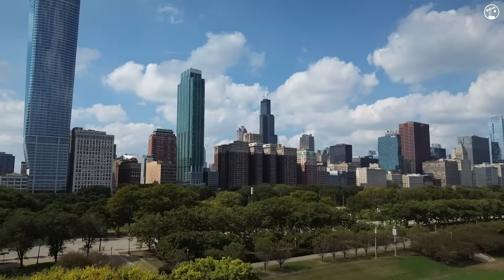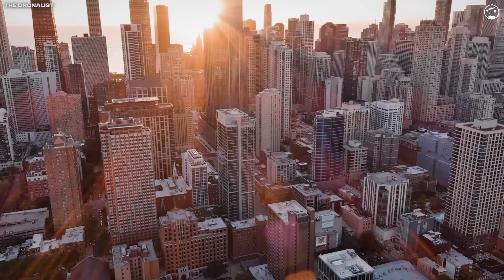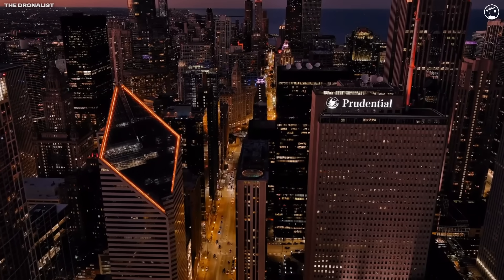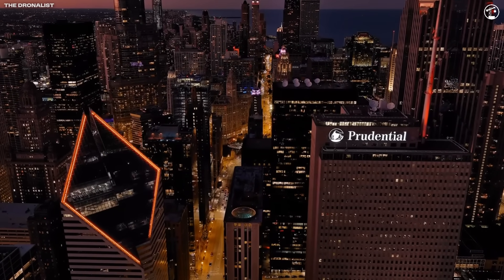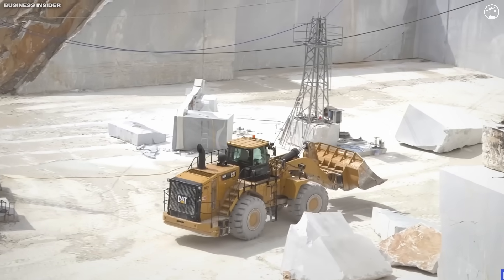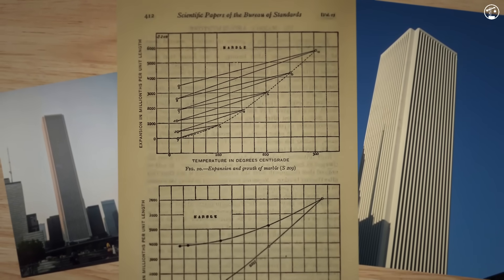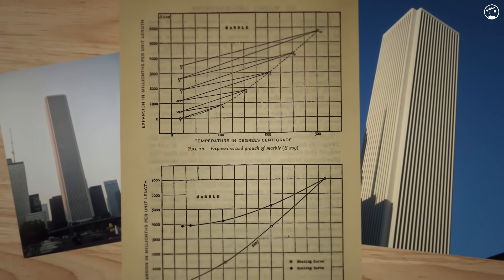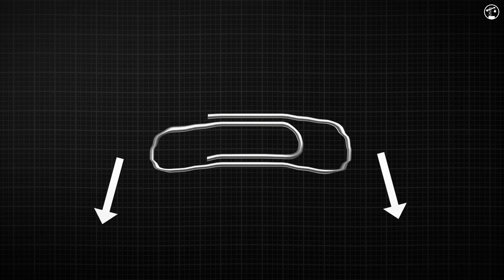Chicago is famous for its windy city reputation, but it also undergoes some serious temperature swings throughout the year. In summer, the facade bakes in 90-plus degree sun, and in winter the temperature can drop into the double digit negatives with bitter winds. That turns out to be terrible for thin marble. Every material expands when heated and contracts when cold, but marble's behavior is tricky. Carrara marble is mostly made up of calcite, and its crystals don't all expand together. Geologists later found that when Carrara marble heats up, it can expand in one direction and contract in another because of its crystal structure. Then it can't snap back perfectly when it cools — it's like bending a paper clip just a little each time. Eventually, it stays bent.